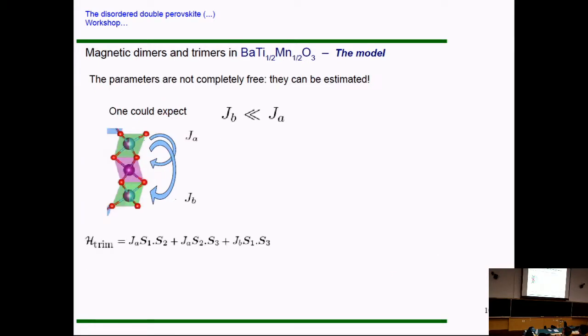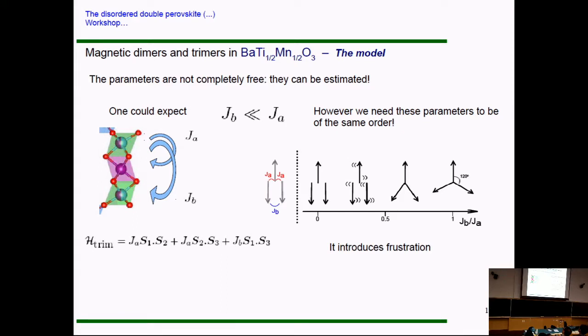So okay, let's go here. You could believe that when I talk about the trimer, you would expect this interaction here to be much larger than the second neighbor interaction. But if you think it through, we have reasons to believe that this is not really the case. Actually, if you use that, you cannot reproduce the experimental data. You have a lot of exchange paths here, and we think that this is the reason that these interactions are actually comparable.